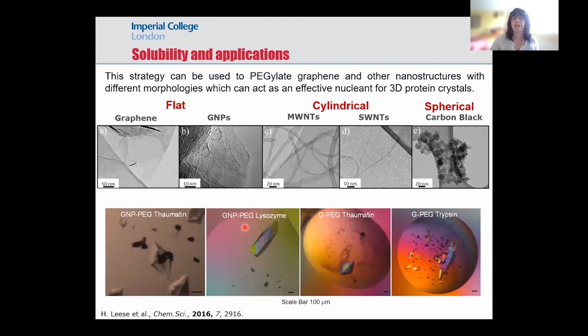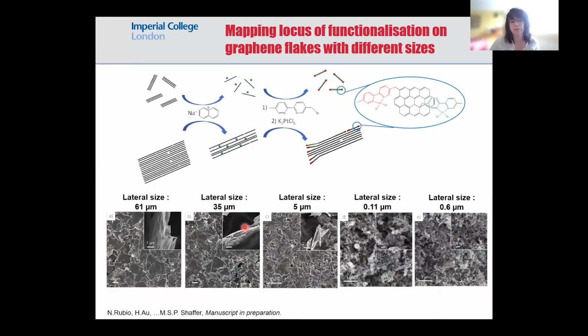So in a different work, we have also functionalized different graphene sizes, as the functionalization is inherent of the starting material. So the choice of starting material is something very important, and sometimes it's not very well addressed in research work. So it's useful to see what's happening as we carry out the functionalization and we decrease the size of the layers. So we use graphites ranging from 61 micrometers down to 100 nanometers. And we charge them, smaller and larger flakes.